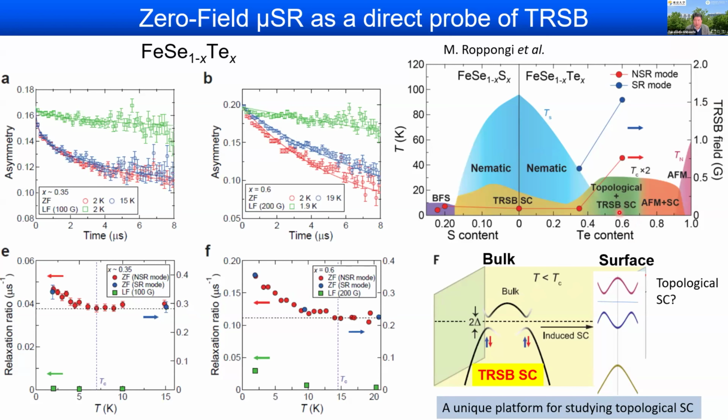No. In this material, there are many pairing interactions, and in terms of symmetry, you can actually have S wave or D wave symmetry which cross. In such a case, you can have time reversal symmetry breaking, such as S plus iD or something like that. So this is nothing to do with the ferromagnetism. So the superconducting order parameter can break the time reversal symmetry.